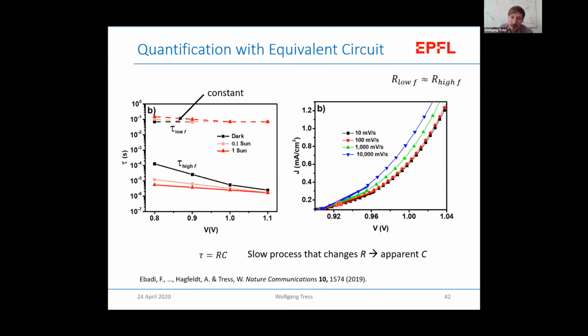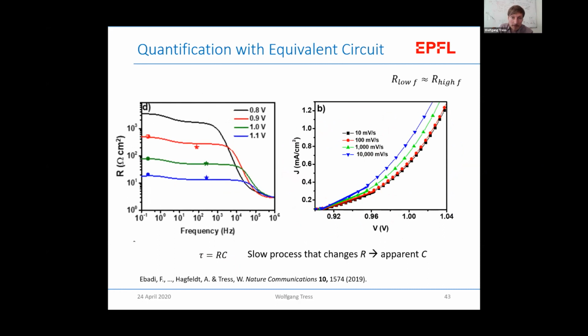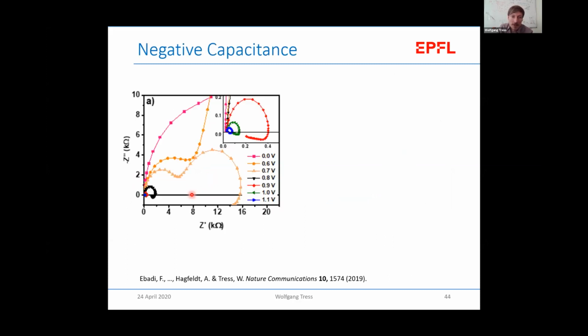In this case, the resistance when you scan faster decreases a little bit. And we can deduce this resistance for fast and slow scan and plot it here, and we can see that they nicely follow, first, the different applied voltages, and then also the fast one and slow one, in principle, this kind of frequency dependence of this resistance.